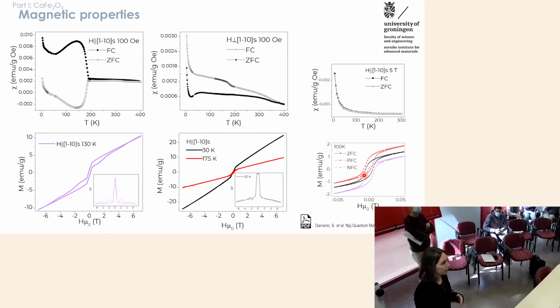What we want to do is also do neutron scattering on the films to actually verify that this is true also for the films. But the general understanding is that the system tends to order in the ground state, which is the B phase, and then the A phase forms due to all these antiphase boundaries in the B phase. And when there is some strain, for example in the case of powders, which are usually obtained by grinding the single crystals, the strain stabilizes the A phase, which is the metastable non-ground state. So our idea is to measure neutron scattering in the films to verify that it is the same case in the films.